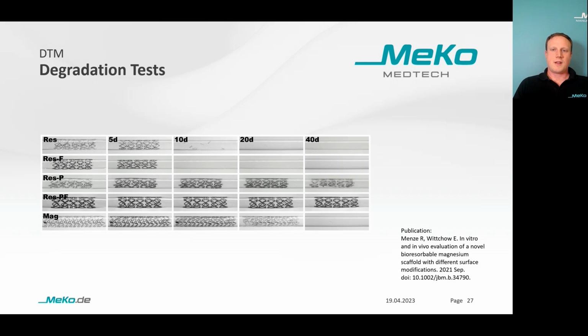With these machines, we are able to test 10 scaffolds in parallel. On this slide, there are exemplary scaffolds shown in the DTM from the start of degradation up to 40 days in the flow. And as you can see, depending on the coating, every row of this table stands for one scaffold with different coatings. The first row is Resoloy without any coating, and then the next 3 rows are Resoloy scaffolds with coating, and the last row down below is a reference CE certified magnesium scaffold. So as you can see, depending on the coating, we are able to prolong the degradation time significantly in vitro. For further information, please have a look at the publication written down here.